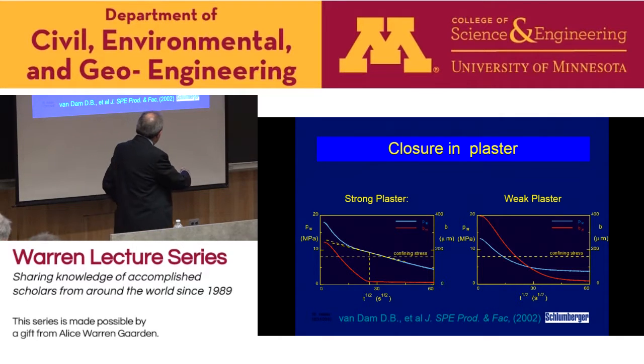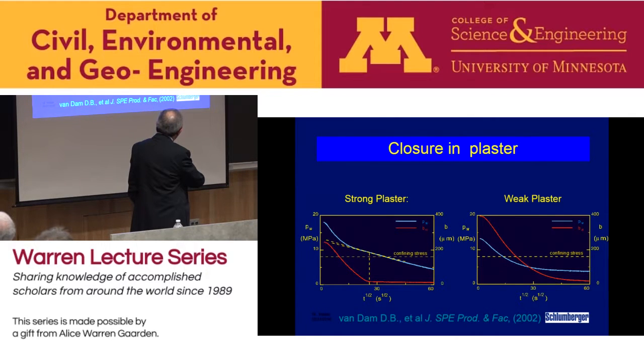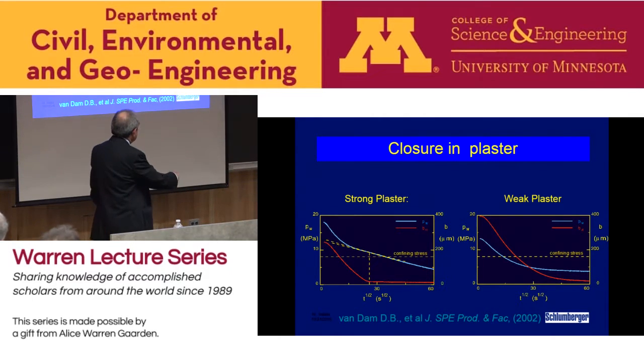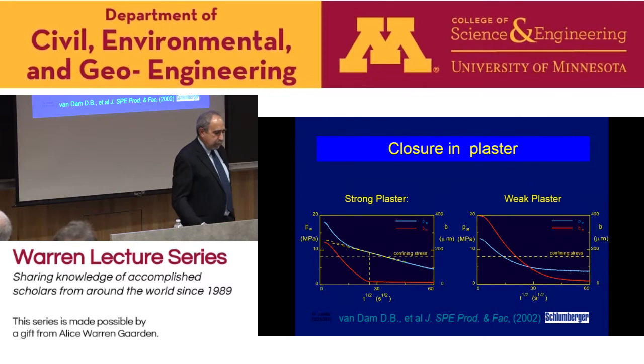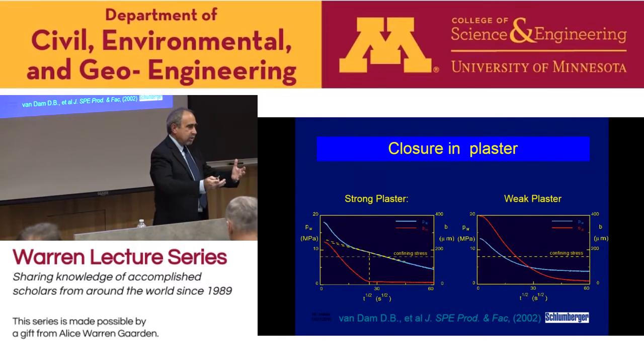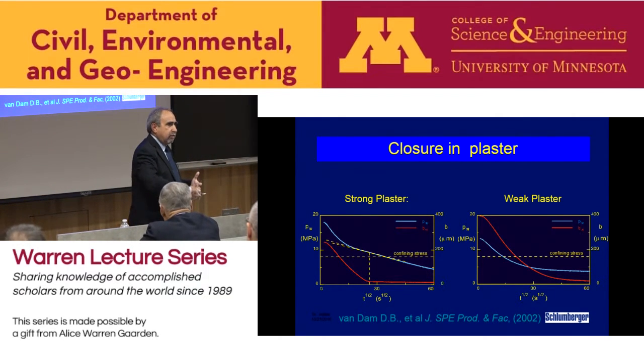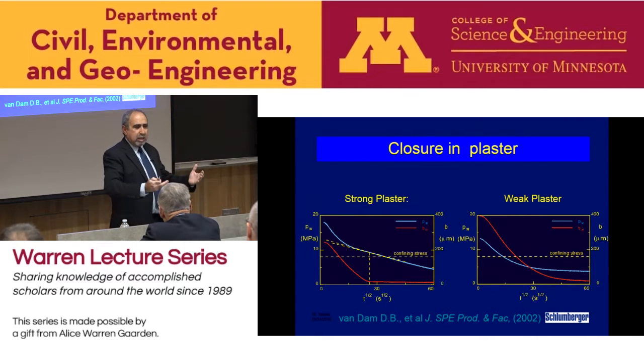If we go to the weak rock, weak plaster, the pattern of the fracture closures, the width, it goes like that. And one will take closure here, that the fracture has closed here. And the corresponding pressure to this value here, it's this one, which is much below the confining stress, okay? And this is a very important result because it's always the discussion we had with Emmanuel, okay, plasticity is important for short fractures, which we understand, because if the fracture gets very long, the size of plasticity relative to the fracture length is not important.